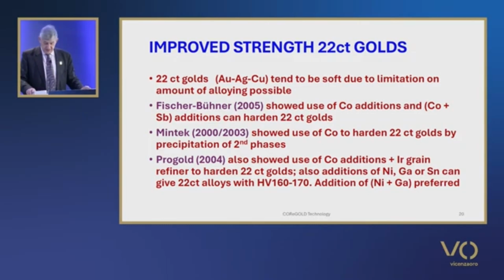Similar work has been reported by Mintek in South Africa. In their 2000 paper, they reported on a new hard 22-carat gold alloy, but gave no details of its composition. It has a colour similar to conventional 22-carat gold, but can attain a peak hardness of 274 Vickers in the cold rolled and aged condition. However, in a later paper in 2003, they describe work on both 99.5% gold and 22-carat gold, that's a gold, copper, silver alloy, in which they study the effects of alloying metals cobalt, germanium, antimony, zirconium and vanadium in hardening them.